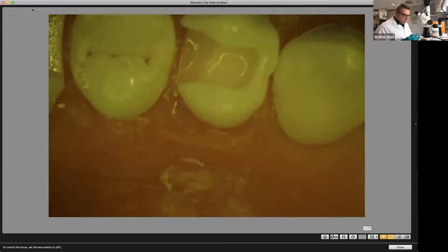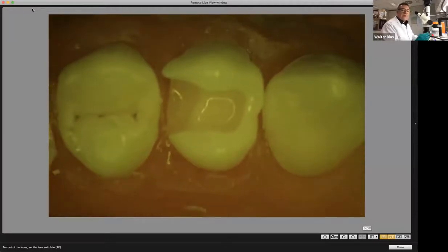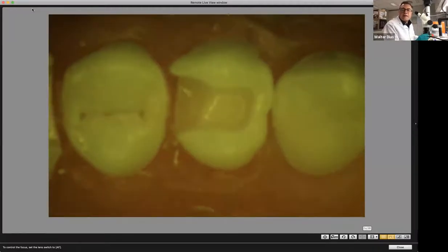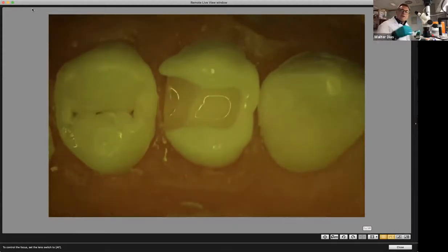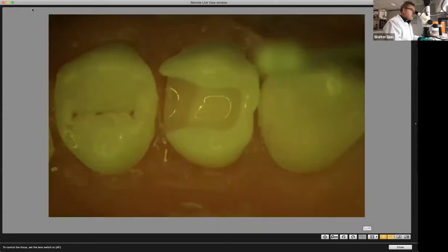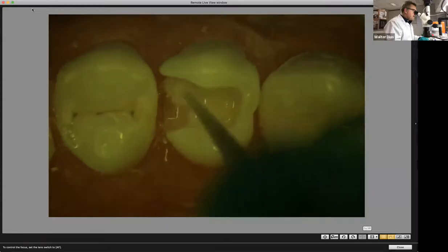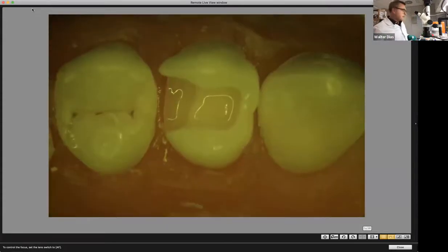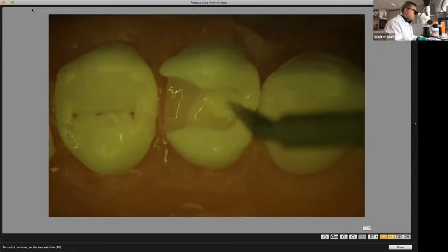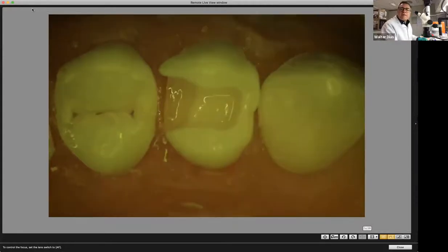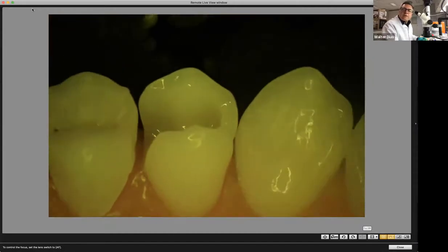And I want to repeat this one more time. The reason that I apply with a little excess is that most of the time I can have full control of the adhesive quantity and I don't have to reapply the adhesive, because the adhesive fully saturates the dentin. What you need to do is, before you air dry, get a new micro brush or a paper point and dry it. Then you come here and remove all the adhesive excess. So in this case, I'm going to get a new micro brush. Okay, remove the excess. Make sure you have a very uniform coating of the adhesive without any excess.